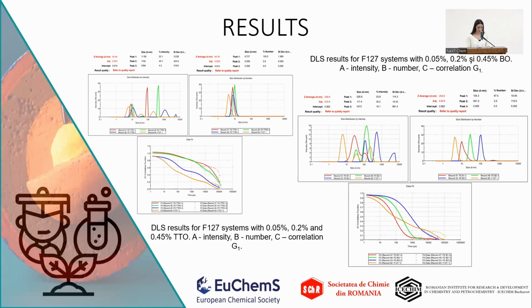For the F127 system, unfortunately, there has been a possible breakdown in micellar structure, meaning that there are some peaks at around 8 nanometers, which means that there are no longer micelles in the dispersion, and there are just macromolecules. For the rest of the F127 systems with bergamot oil, I can say exactly the same thing. With the increasing concentration, we managed to encapsulate more essential oil.